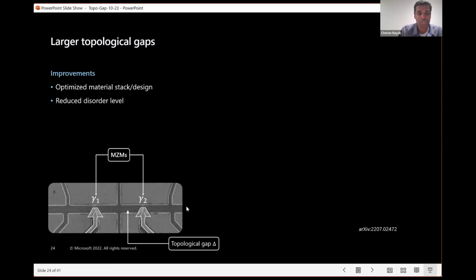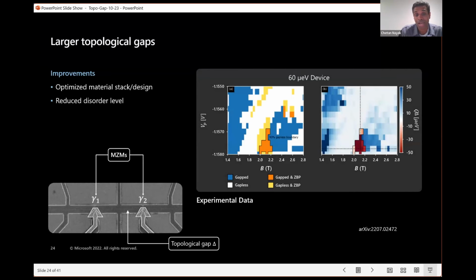And then with the single plunger gate here, we need some additional second layer gates over the junctions in order to enable junction operations that you could fully open and fully close, even while the single plunger gate was being pushed fairly negative. And we actually saw in this new design a device with quite large gaps. So here's a device with a 60 microvolt topological gap, and here's a topological region in this phase diagram.